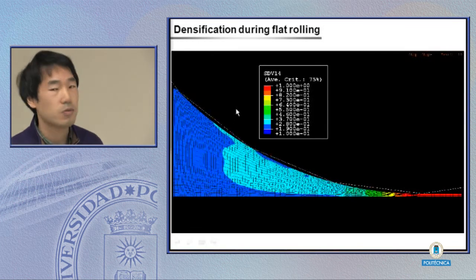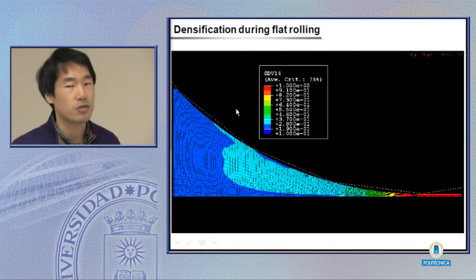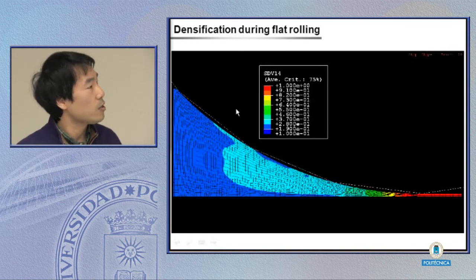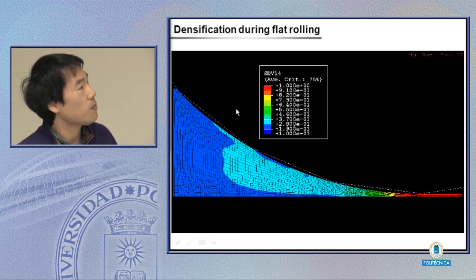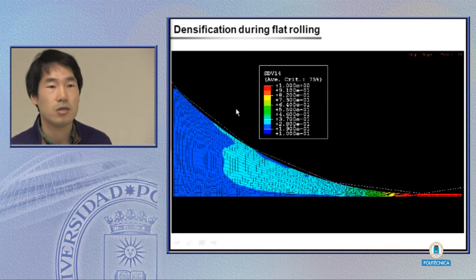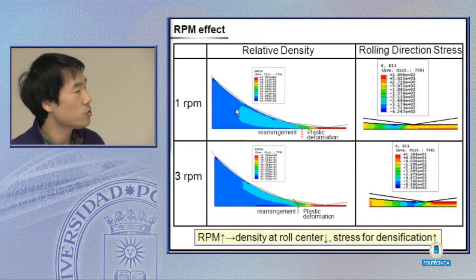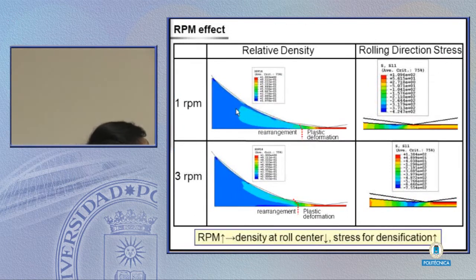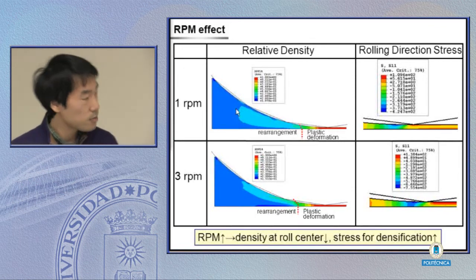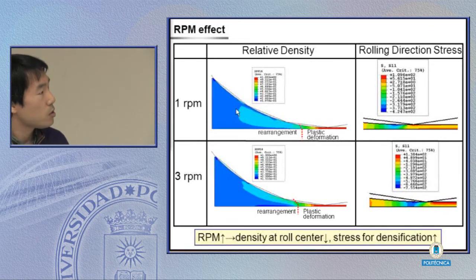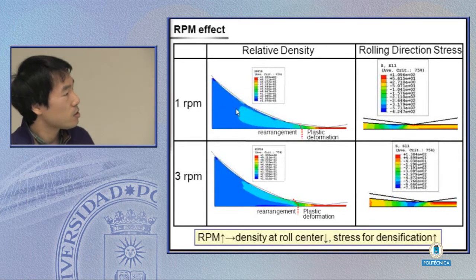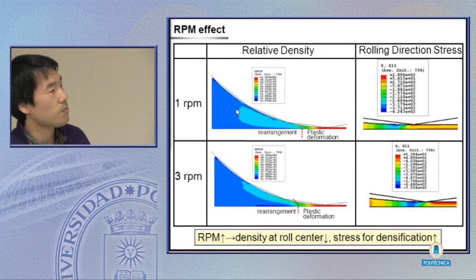So here is the result of densification during the rolling. At the beginning, it begins with very low density, but during the powder compression, you can see the powders begin with very low density, but they are compacted after the compression.